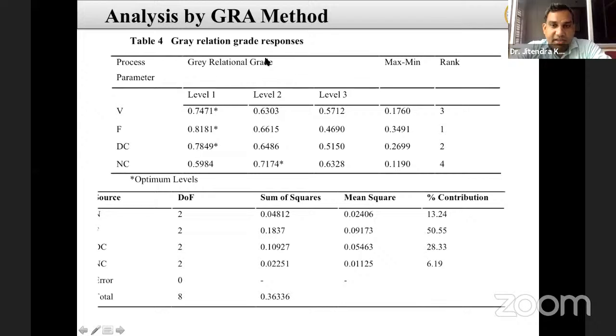We further give the rank for those three levels according to velocity, feed, depth of cut, and nanoparticle concentration, and according to that we get the optimum parameters, whatever the cutting forces and the surface roughness we have obtained. So this is the cutting speed, which I think is cut here. So the first term is the cutting speed, then feed, depth of cut, and nanoparticle concentration.